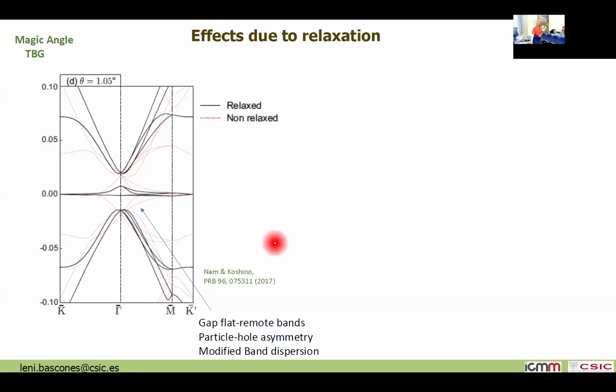But here you can have an idea of what happens if you consider the relaxed or the non-relaxed structure. If your lattice is not relaxed, you will have these red lines. If you relax it, you have the black lines. In terms of what is most important for the correlated states, if you don't consider the relaxed structure, you can see that these red lines, the flat bands, are not isolated from the remote bands. So this is specifically associated with the band structure changes from relaxation.